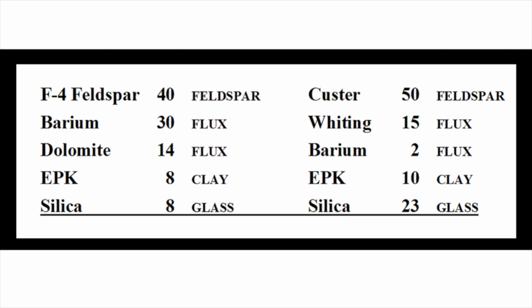Note that the feldspar is the bulk of the content in both glazes. Secondly, barium, which is the main flux of one of the glazes, promotes a matte surface. Thirdly, the second glaze is much higher in silica. So which one is the matte glaze? The glaze on the left is matte and the glaze on the right is glossy.